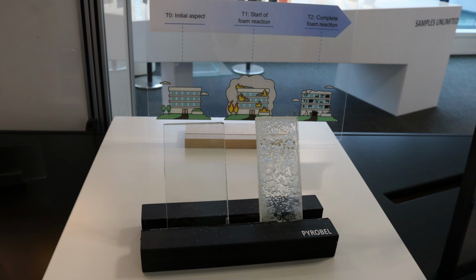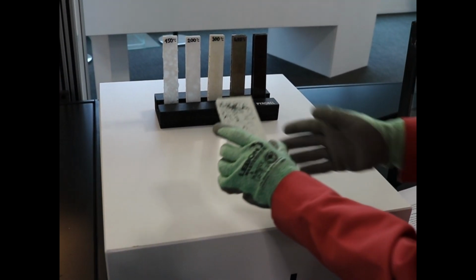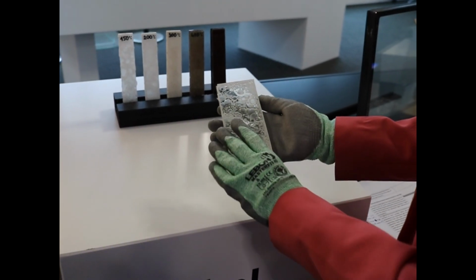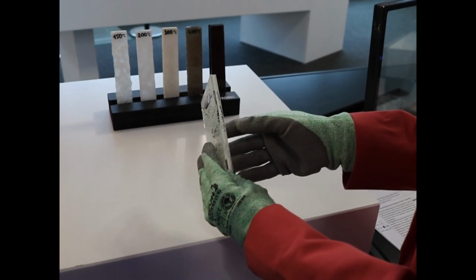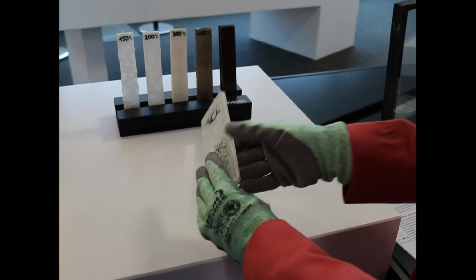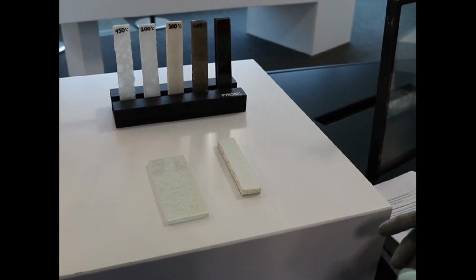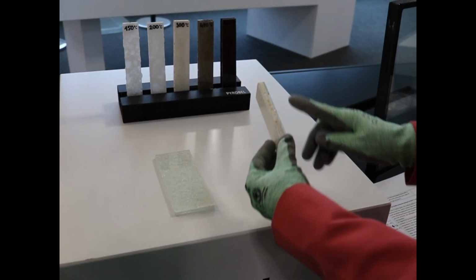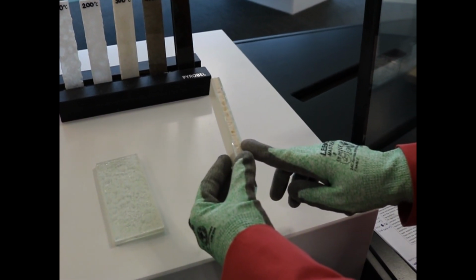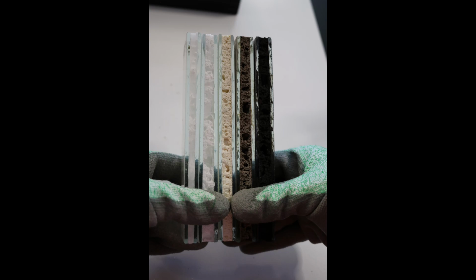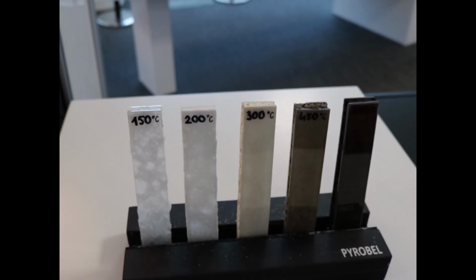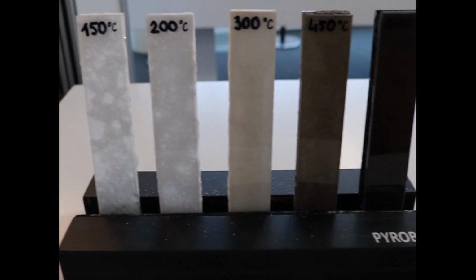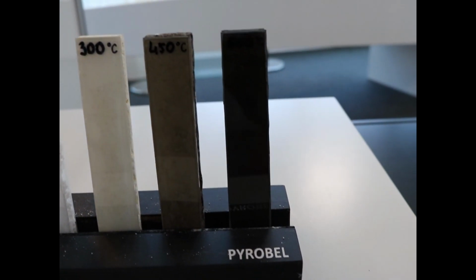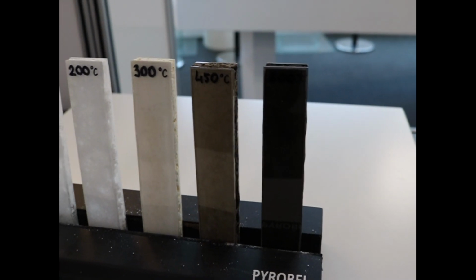When exposed to high temperature, the intumescent gel undergoes different reactions. First, free water captured inside the gel starts vaporizing, creating big pores and triggering the gel's expansion. Next, the bond water is removed and the layer expands even more, creating a porous opaque foam which stops the heat transfer through the glazing. There are also some smaller reactions coming from other components which continue until the temperature around 600 or 700 Celsius degrees. Above this temperature, the foam starts flowing.